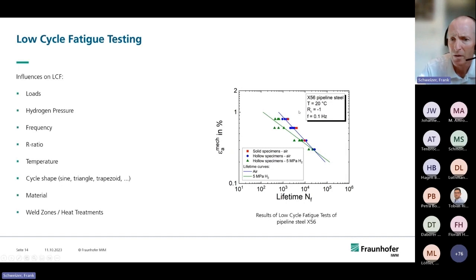So what you see here, solid specimens in air is red dotted. Then you have the hollow specimens in air, and you see that this lies together, so you can use solid specimens or hollow specimens. And then we had 50 bars of hydrogen in the X56 steel. And you see that on the x-axis you have the cycles, and on the y-axis you see the straining of the material. This is all at room temperature at a quite low frequency. And yeah, the steel shows a bit of changes due to hydrogen.